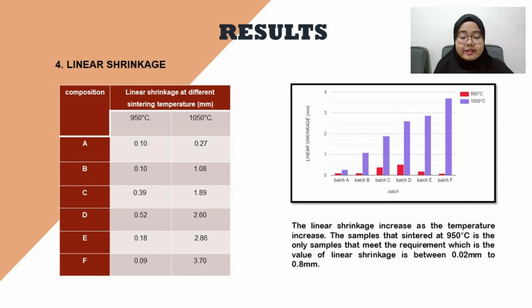The last one is the result for linear shrinkage. The linear shrinkage increased as the temperature increased. The sample that was sintered at 950 degrees Celsius is the only sample that meets the requirement, which is a linear shrinkage value between 0.02 mm to 0.8 mm.